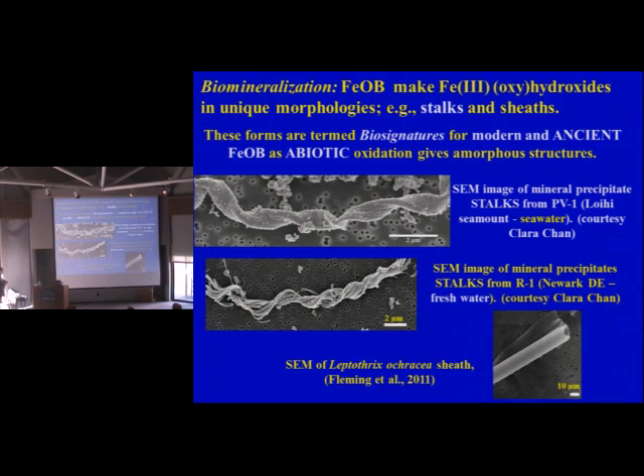You'll notice little precipitates right here and there. That's the amorphous abiotic precipitation, because even though oxygen's present and the organisms are present, there's still chemical oxidation going on. So we want to discriminate between the chemical and the biological, which is most prevalent. As you'll see, it depends on the conditions that you provide. So you notice that there is still some amorphous precipitation going on, and that we believe is entirely due to chemical oxidation, whether it's chemicals in solution or chemical with autocatalysis with iron oxides.